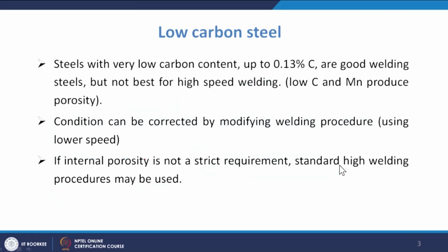Okay. So low carbon steel, steel with low carbon content up to 0.13 percent, is a good weldable steel, but not best for high speed welding. Why? Because high speed welding generally produces porosity. If our component is not affected by the presence of porosity, then we can go for the higher speed also. The condition can be corrected by modifying the welding procedure, that is using a lower speed. So if internal porosity is not a strict requirement, then the standard high speed welding procedure may be used. So if the porosity is not a big problem, then we can go for high speed also. So generally low carbon steels have good weldability.